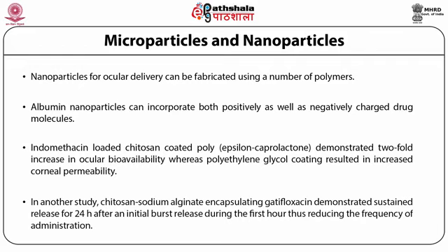In another study, chitosan sodium alginate encapsulating gatifloxacin demonstrated sustained release for 24 hours after an initial burst release during the first hour, thus reducing the frequency of administration.